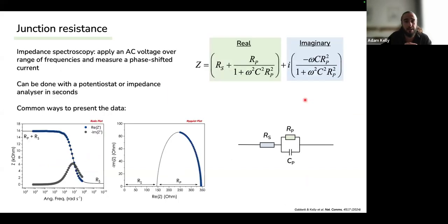So this means that we can apply a technique known as impedance spectroscopy. This circuit model here is known as a Randles circuit. It's very well known, very well understood. It can be analyzed using these equations here. And we can perform measurements with impedance spectroscopy using a potentiostat or an impedance analyzer, and the measurement takes seconds.